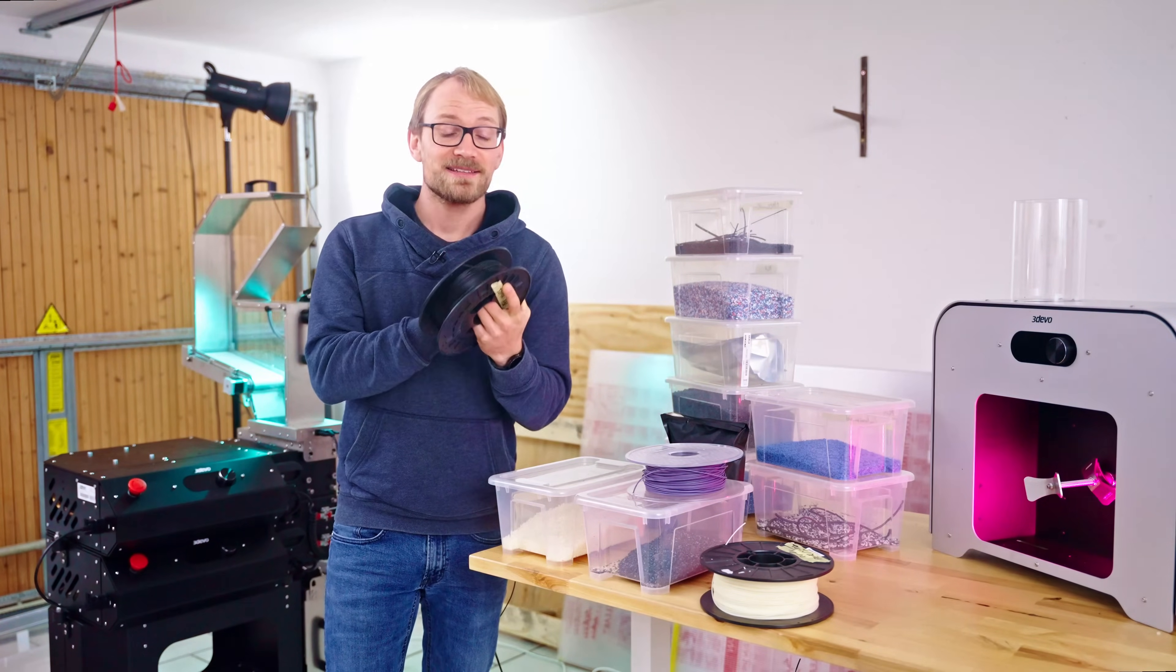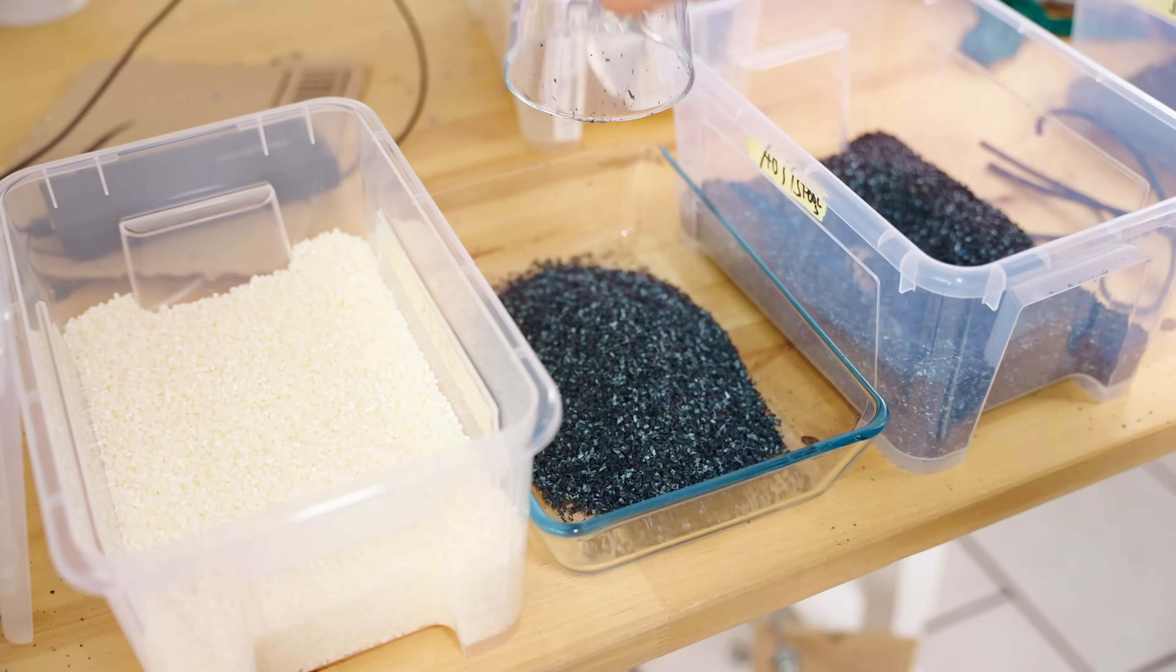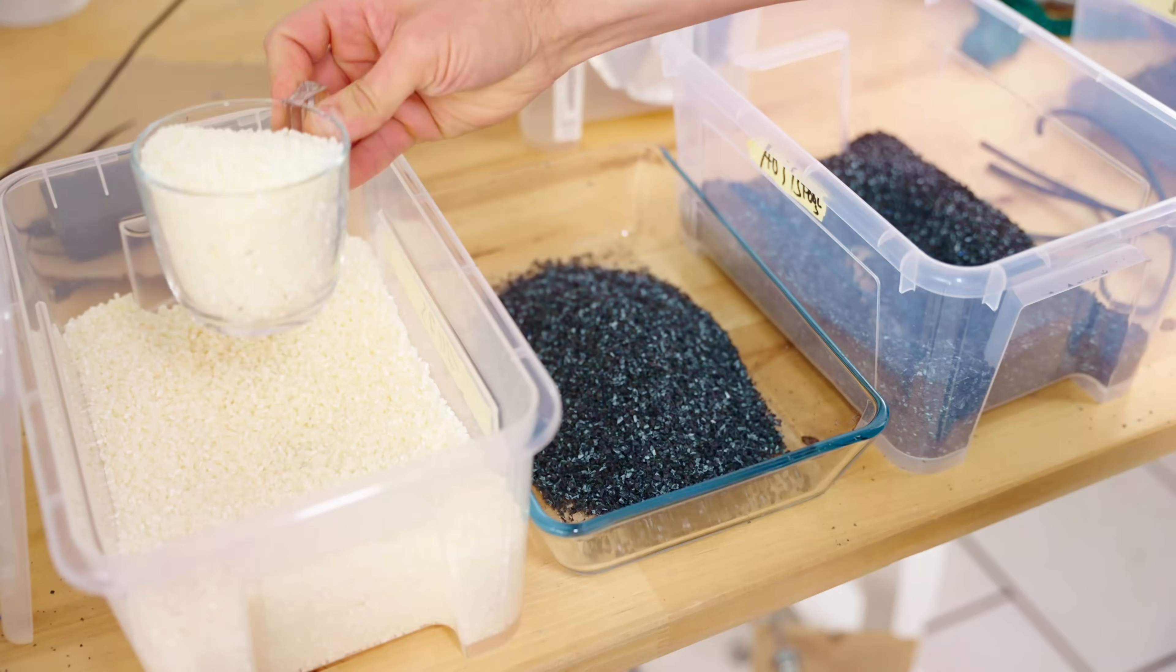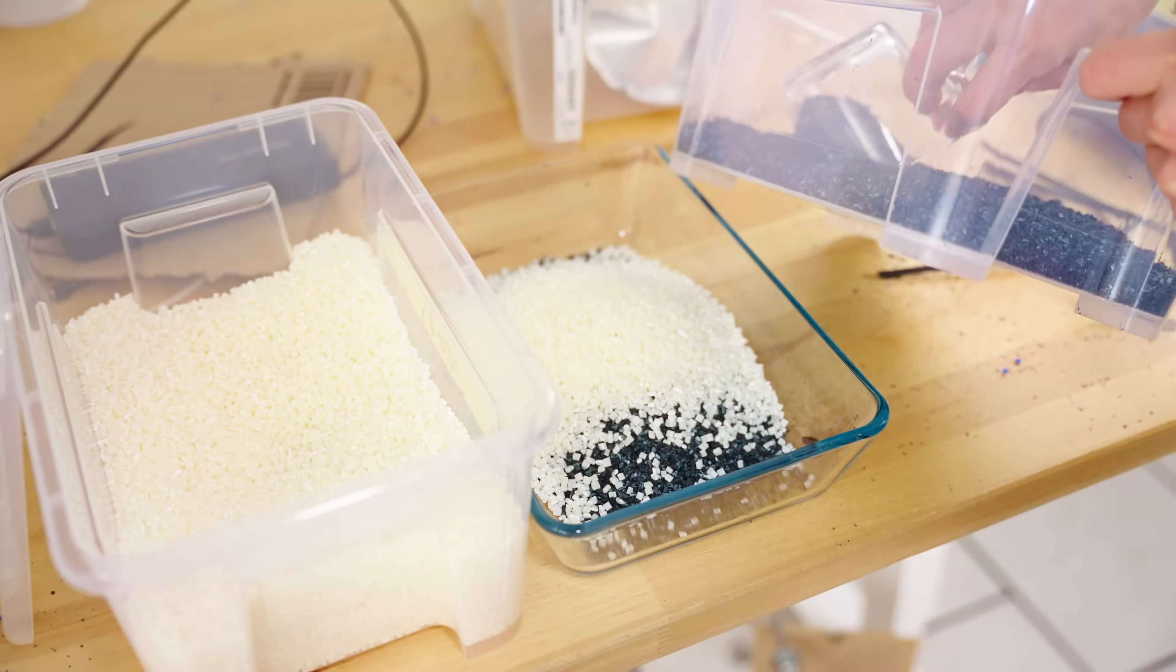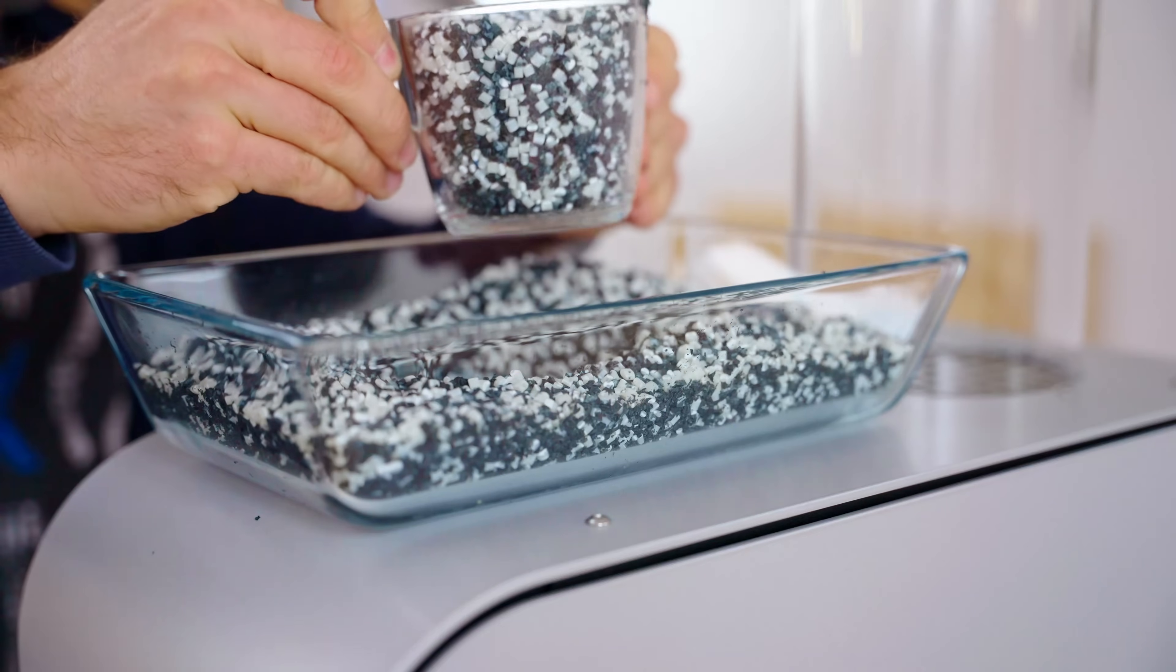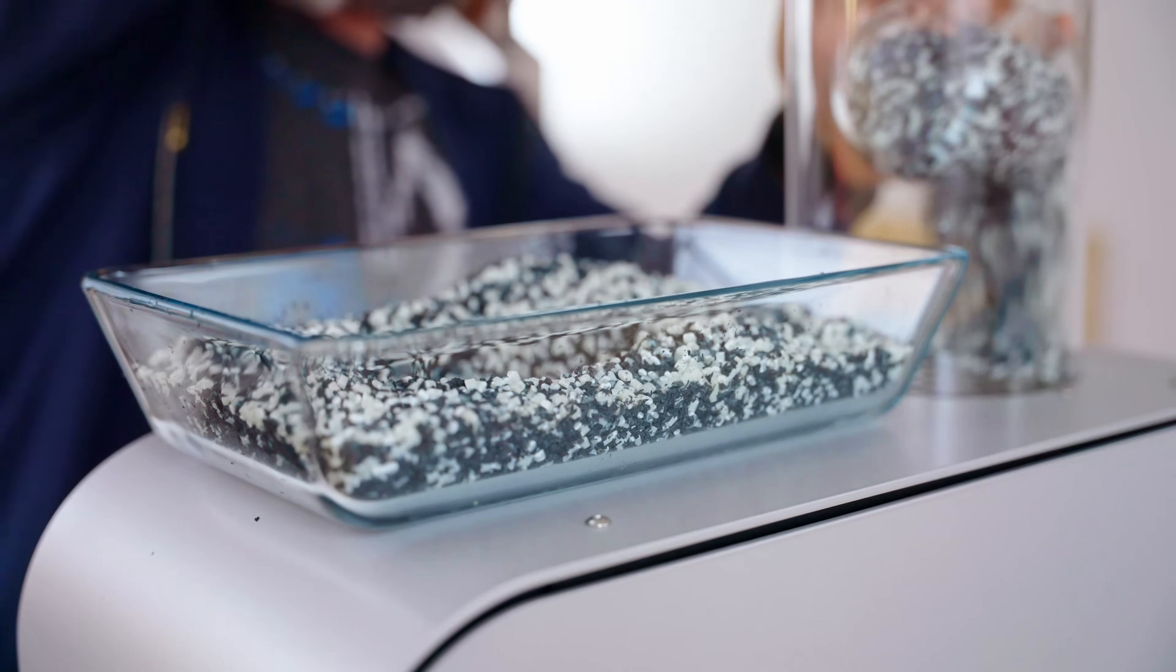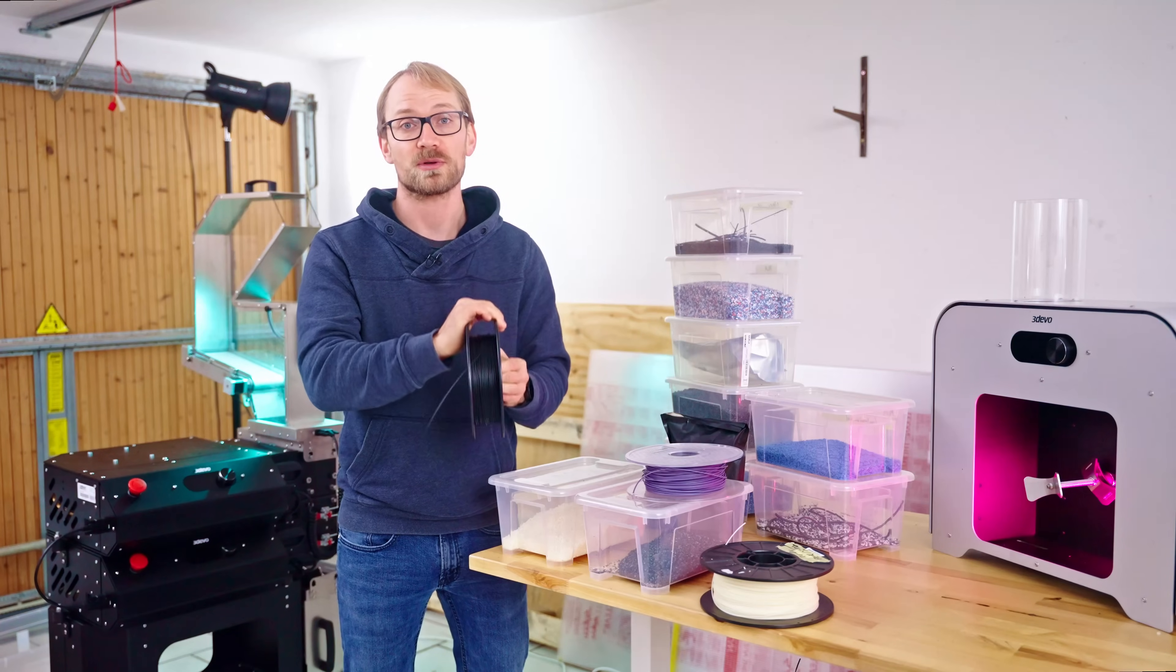And the other one is the ABS spools, but instead of doing just the recycled material, I used a special recipe of two cups ground spools, two cups PolyLac ABS, all baked at 70 degrees Celsius for two hours, and out came this perfectly fine spool of not-quite-black ABS, and it had none of the surface tearing issues that I got with only extruding the shredded spools.